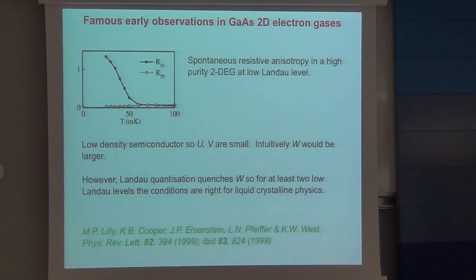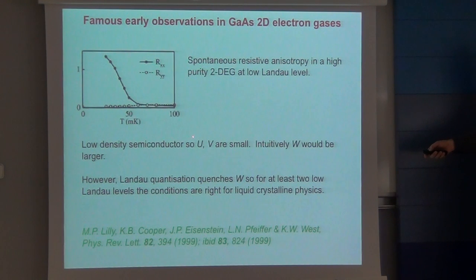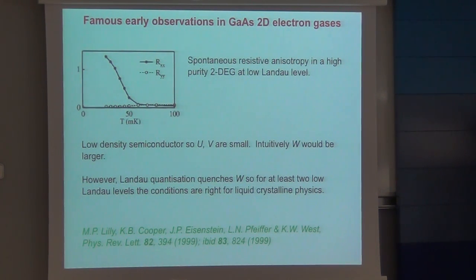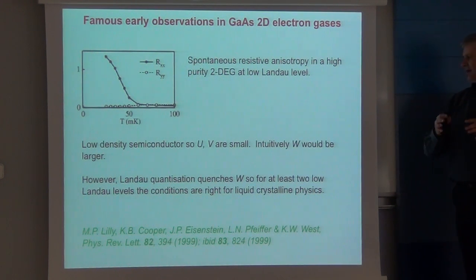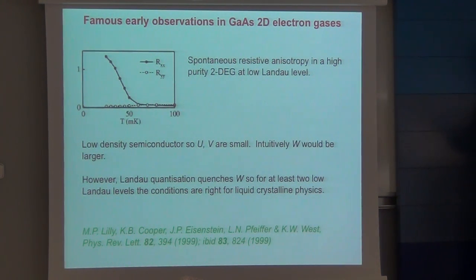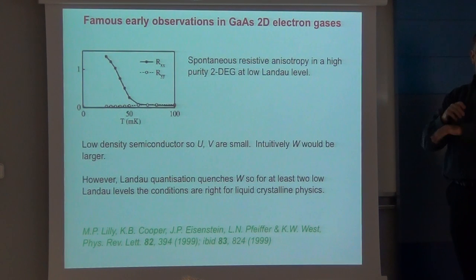So you might ask yourself, why is this happening? And here I think it's where you get to these energy scales. This is a very low density semiconductor, so U is very small. The interaction term compared to a correlated material is very small. So is V, because you're down at some very long wavelength where you're not feeling the lattice at all. So you would think that W would dominate and you'd get nothing interesting going on at all. But of course the essence of all the interesting physics that happens in high magnetic fields is that when you split into Landau levels, you kill the bandwidth. So you kill the kinetic energy by putting things into Landau levels. If you kill it well enough, you get the fractional quantum Hall state. But these 2 Landau levels appear to have just achieved the balance to be just right, so that the leading instability is a Pomeranchuk distortion of some kind. It's an instability towards anisotropic transport.